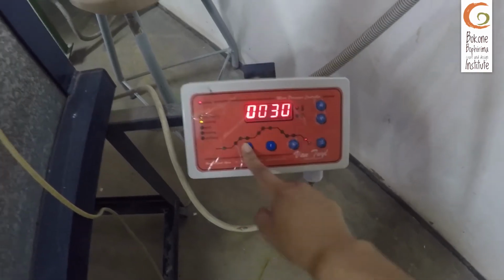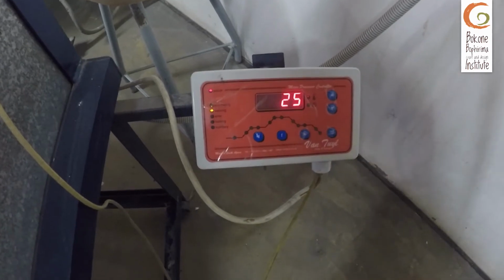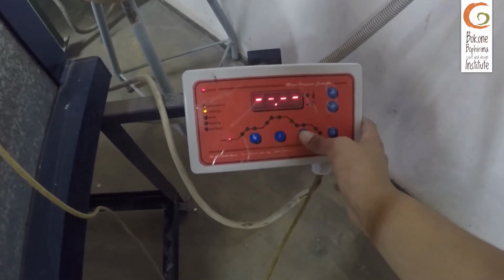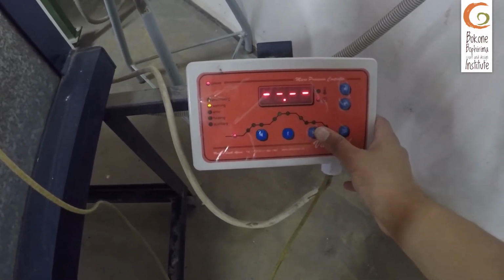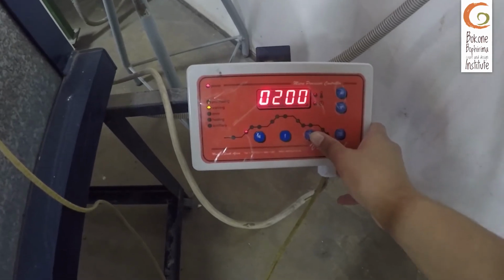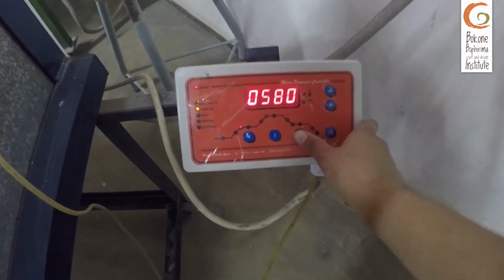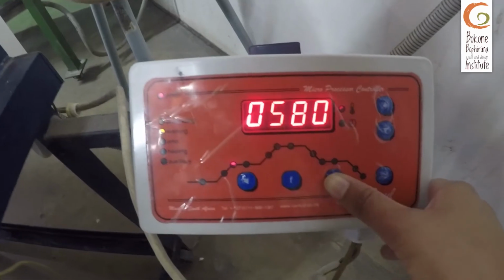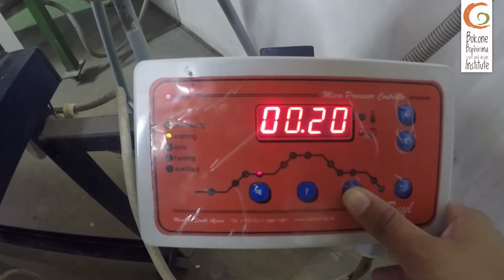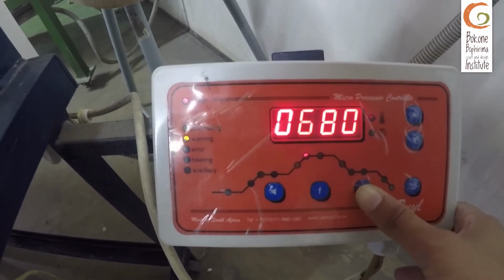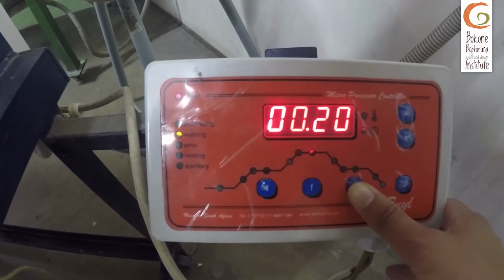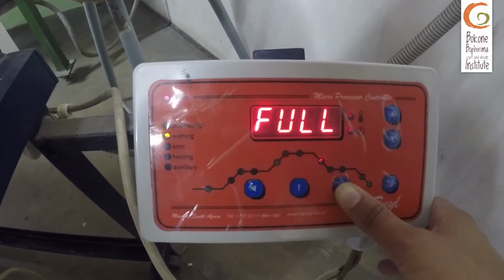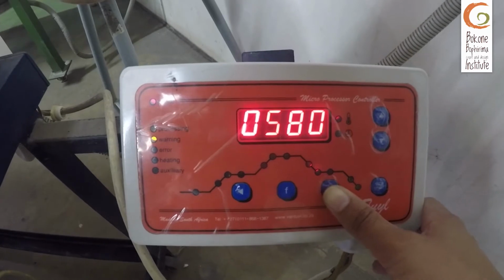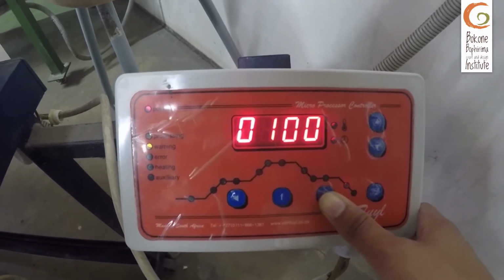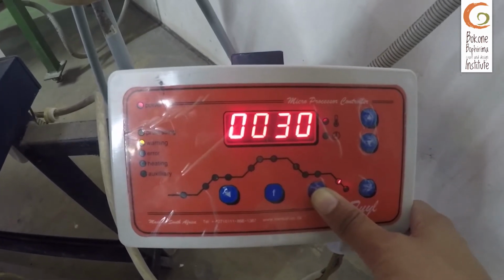We're starting immediately. We're going up at 200 degrees per hour to 580 degrees Celsius, letting it soak for 20 minutes, going up the ramp at 250 degrees to 680 degrees, which is top temperature, letting it soak for 20 minutes, coming full down to 580, letting it soak for 30 minutes, coming down at 100 to 30 degrees.